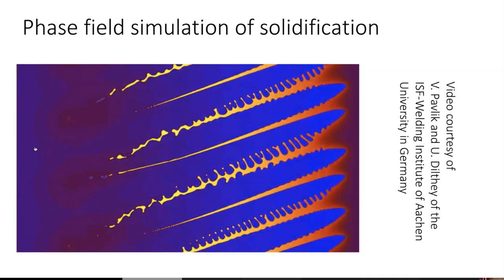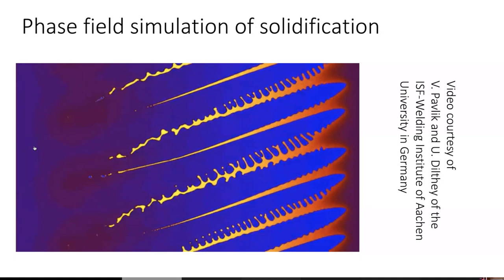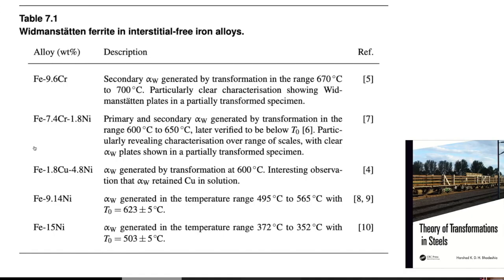Finally, in order to produce a shape, the phase field models use ridiculous levels of anisotropy of interface energy. In other words, the shapes are not naturally produced, but by forcing a certain anisotropy into the system. So here, for example, are all the alloys in which I have found Widmanstätten ferrite forming